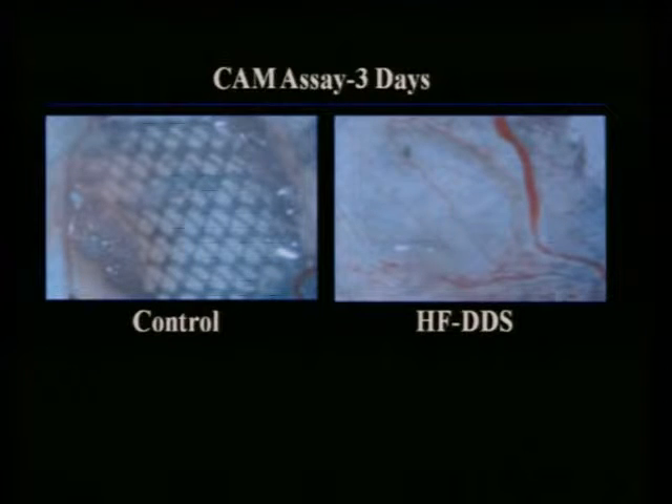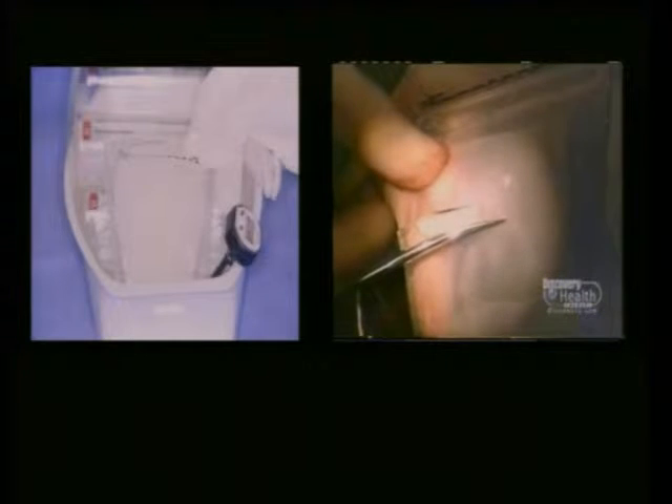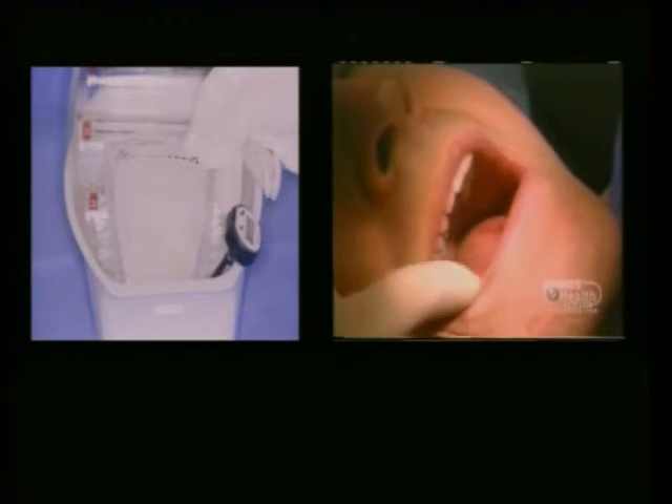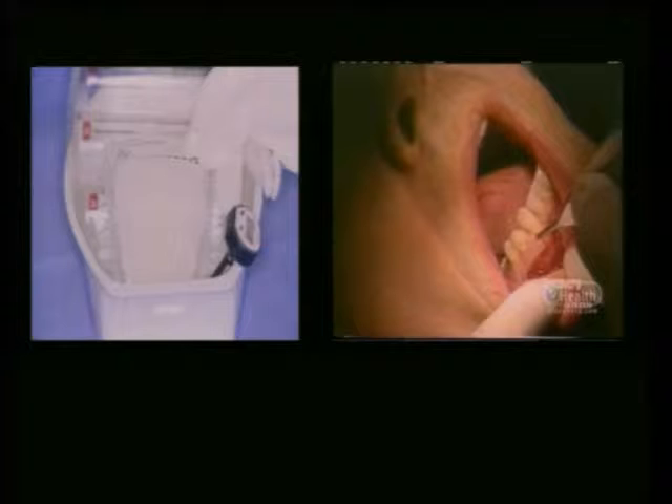This particular material is cryopreserved in a little bioreactor. Through a rapid thaw, you can bring it back to life. Pivotal studies show that when you bring it back, it's still producing the glycosaminoglycans, cytokines, all of those things in therapeutic range. This is what it looks like after it has been thawed. We're in the process of cutting out a little piece to use on a graft. The cells and all the proteins are on this little piece of Vicryl.